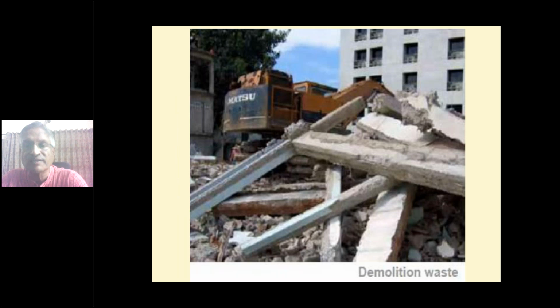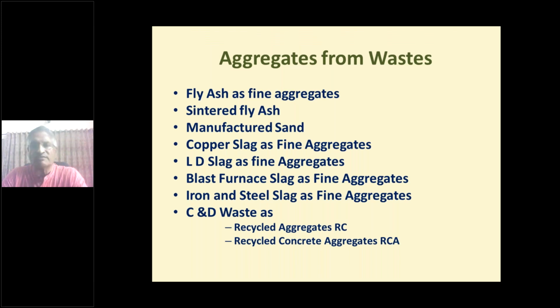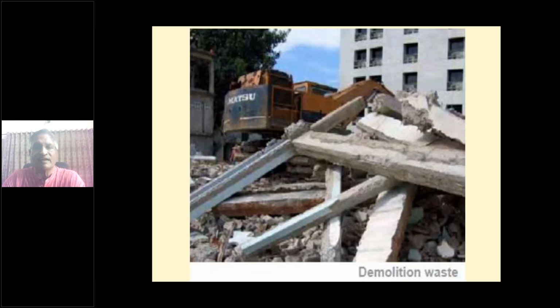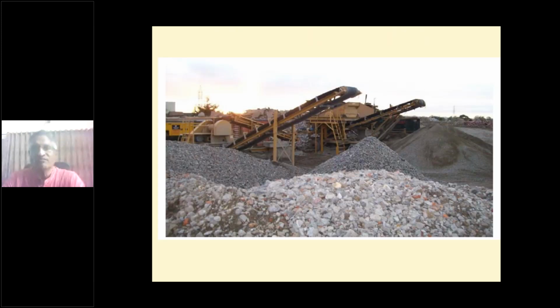So this is the kind of demolition material that comes, when we see at the site, but it can be taken to the field. This is a Delhi plant which has been put up by the municipal corporation. Another has also come in the eastern side, which has been recycled into, you can see, different sized aggregates. This is the site where it has been recycled and kept.